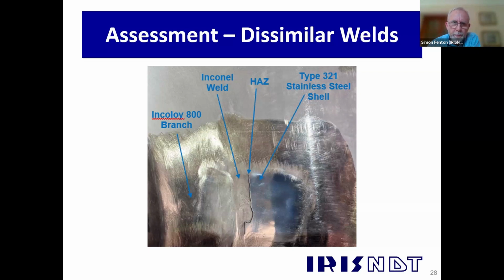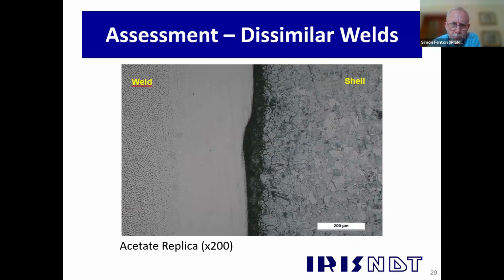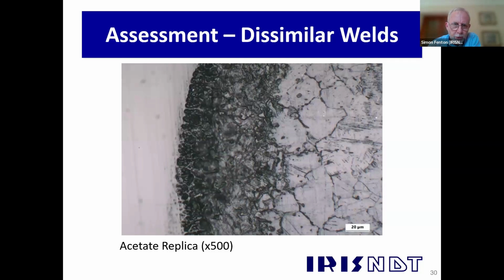Now, if we look at the next slide, Pete, we can see a times 200 replica of what was seen across that fusion boundary. So on the far left, we've got an etched weld structure. On the far right, we've got the etched 321 parent shell material. And next to the weld, we've got this region that's not been etched, a very dark region that's been etched next to that. And then on the next slide, Pete, in more detail at times 500, you can see that darkly etched region has actually got a substructure to it. So it looks like there's carbides in there, possibly. You can see the twins on the far right hand side. So there is a substructure to that.